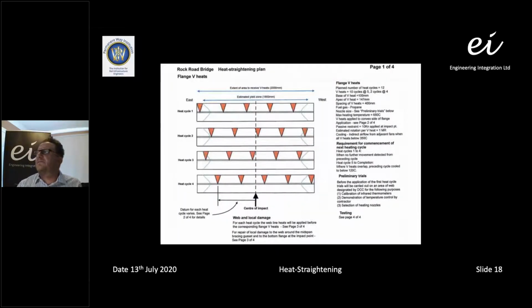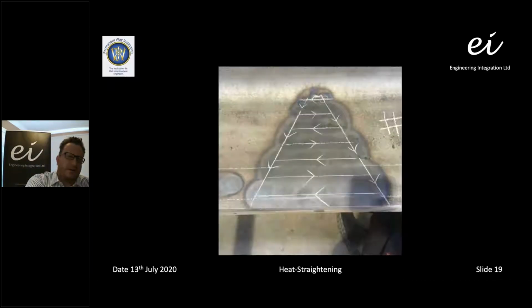This is typically some V-heat patterns that we would apply to the bottom flange of the girder, and you can see there that if you overlaid all of those heat cycles, you would get quite a concentrated set of V-heats applied to that bottom girder, and that's typically what we would do when you've got deformation of this type. To look in more detail at the actual heating pattern associated with the V-heat, you can see there that the operative uses the arrows to follow and apply the heat in the girder, basically washing the girder from the web and working away to the edge of the flange.